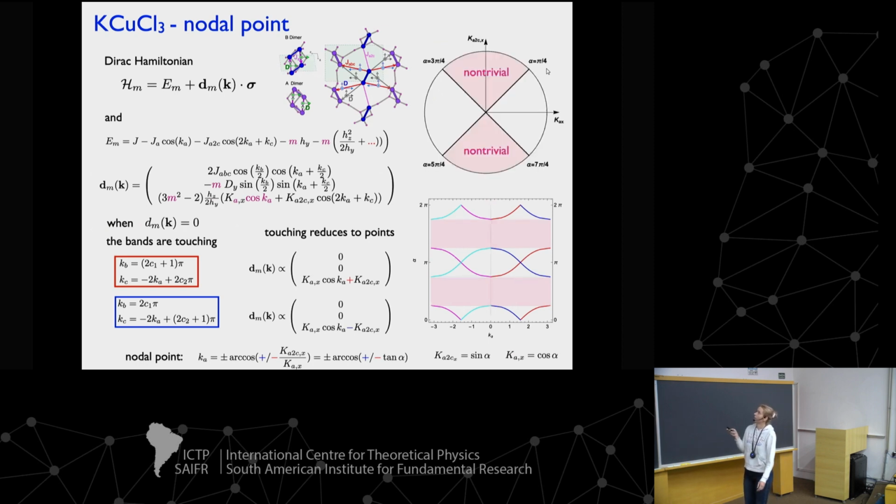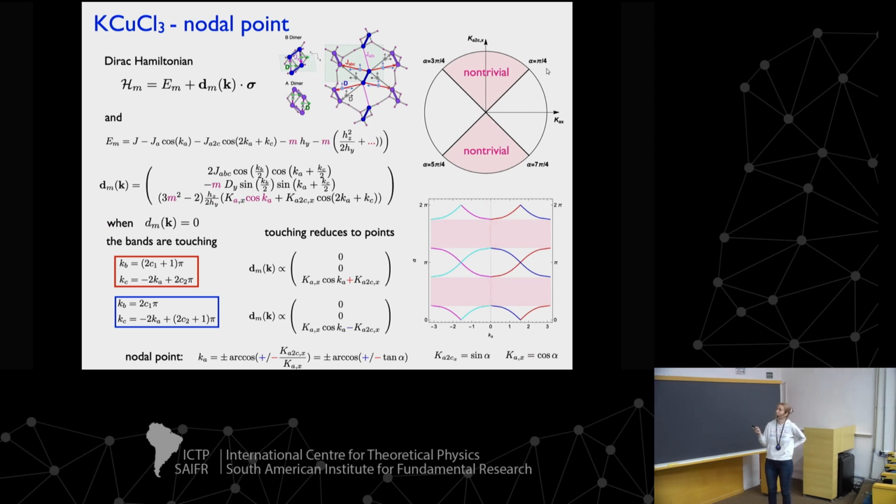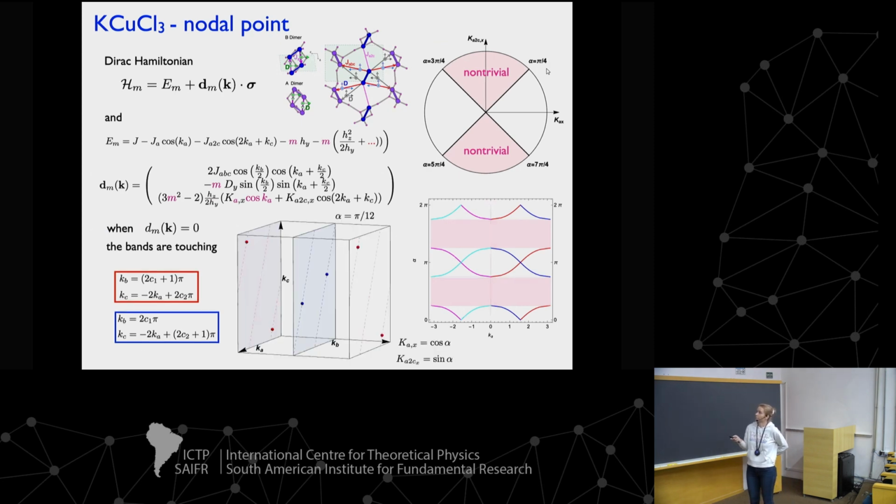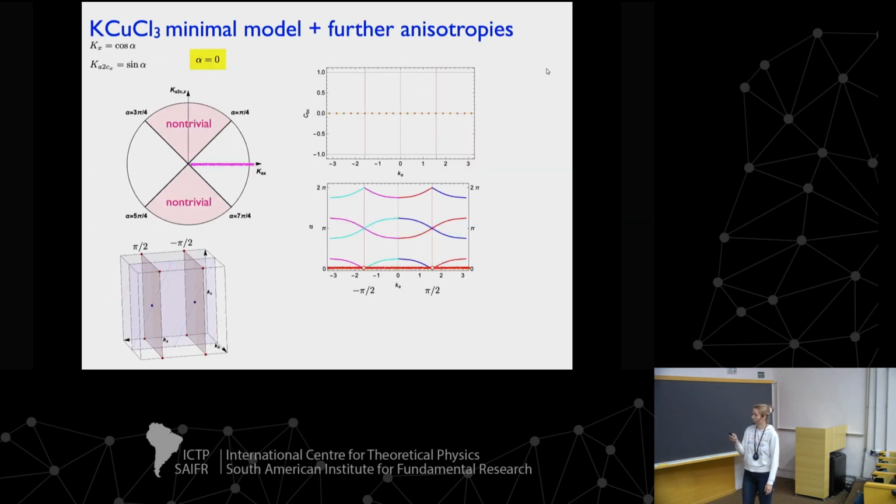And again, we have a similar diagram for this parameter space. Now the pink region is, again, where we can't satisfy these conditions and the system is fully gapped, or all of the bands are fully gapped. And then the white region is where we actually have Weyl points in the system somewhere. So this looks something like that. These dashed lines used to be our nodal lines, and of course they're not surviving. There are just points where we will have the degeneracy.